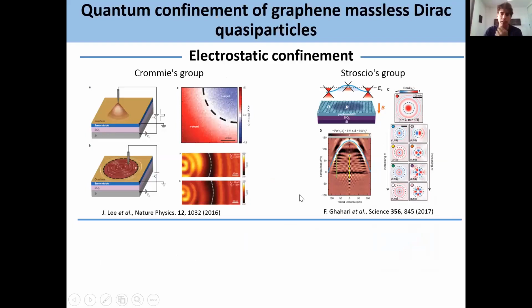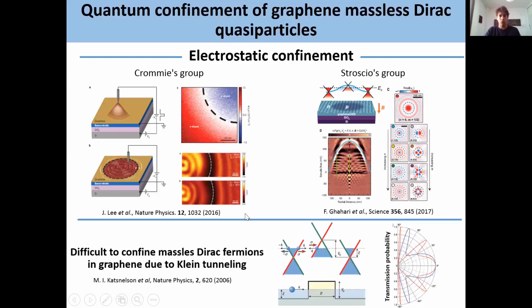Much more recently, we had these really beautiful experiments where they use electrostatic confinement. This was pioneered by the Stroscio and Mike Crommie group, where they made these charges embedded in the silicon oxide, and they were able to change from N-doping to P-doping, and this was giving them some electrostatic barriers. They were able to see these standing wave patterns and do a series of really exciting and very beautiful experiments. However, electrostatic confinement has the problem that I was telling you at the beginning, that it is very difficult to completely confine massless Dirac quasiparticles. In some directions, they will always escape. And also, as far as I know, it was not so easy, or not even possible, to decide exactly the shape of your confinement barrier. So we still had some room to do something in this job.